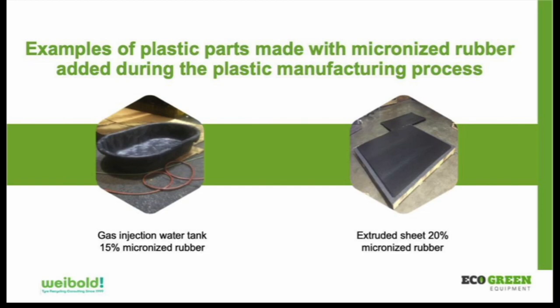The part on the right is an extruded sheet with 20% micronized rubber. Again, this is rubber going directly into the extruder, but it's a mixing extruder. In this case, it was a single screw extruder, but it was used for doing recycled materials. So it had a special section of the screw that, like a twin screw machine, would create very good mixing within that small segment. And because this was just being produced as a sheet to then die cut out mud flaps for semi trucks, it worked very well. But again, very uncommon to be able to introduce that directly in.